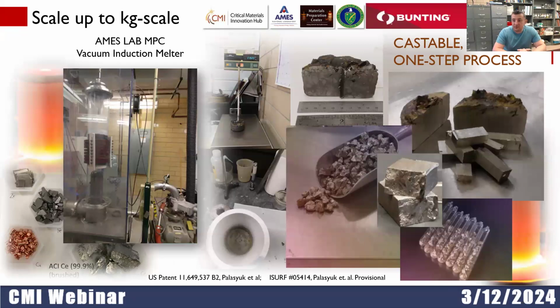So we decided to try to scale up the system, and we decided to try to cast it. And this was done within the TCF project, where we worked together with Bunting Du Bois. We were doing the casting part of this, and Bunting Du Bois was trying to make a bonded magnet out of the powder, which was received from casts. And it was successful. Casting was successful. I will just touch the casting part of this project. In fact, we were able to reproduce the material which showed practically lab reference characteristics, and we were able to use commercial cerium for our experiments.